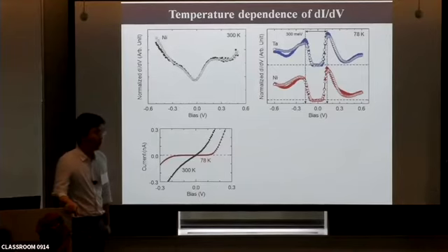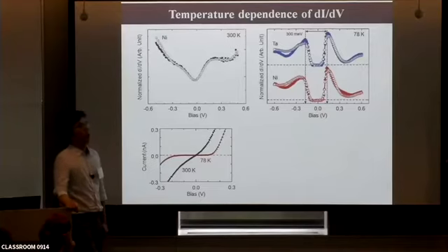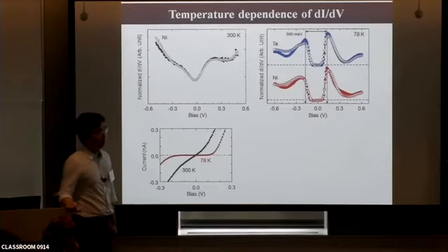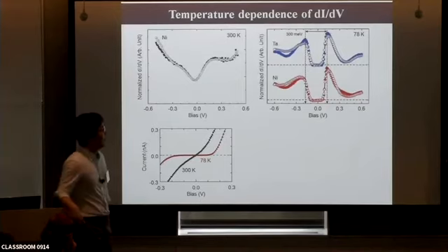in the excitonic insulator phase there is a symmetry breaking, inversion symmetry breaking, which leads to a little bit of structure in the density of states, the point of minimum band gap is not exactly at the gamma point. There's a little bit of asymmetry. So my question, would that show up in a QPI measurement, which sort of shows the Fermi surface? Is there a way to see that in your experiments? I mean, it's a delicate effect, it's long wavelength, but could you see that off-centering somehow, for example, by QPI?